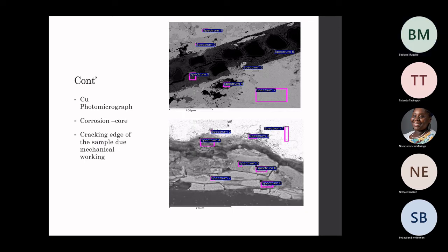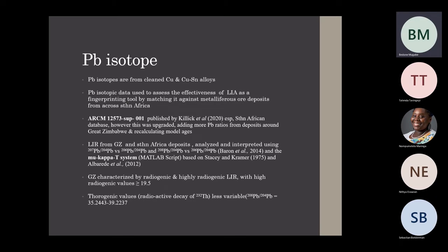Next slide, please. So after going through all this, and after having an understanding of the composition of the samples, what I then did was to take the samples for MC-ICP-MS for lead isotopic characterization. Most of the samples that were analyzed for lead isotopes were cleaned copper and low tin bronzes. This process was also to assess the effectiveness of fingerprinting, of trying to determine the provenance of these metals to certain metalliferous deposits.